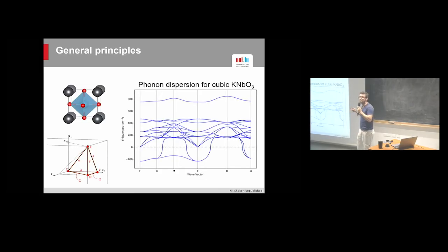We haven't seen so many of those so far, right? So those are phonon dispersion branches. Standa had the one for, I think it was STO, right? Yeah, that you were showing. Here is another one just as an example, and I will repeat this because it's really important. So what those theory people do is that they take their favorite DFT code. In that case, it was VASP, I think, but whichever. And they compute the phonons in the cubic phase. This is for potassium niobate.